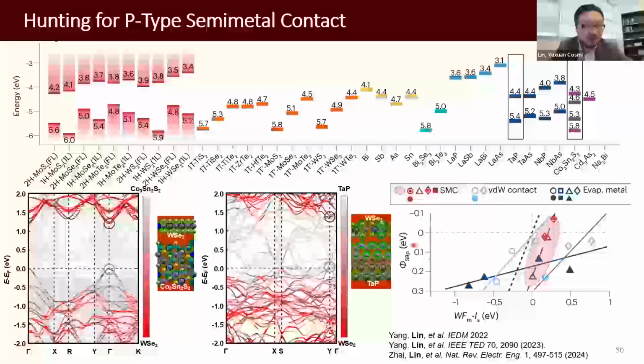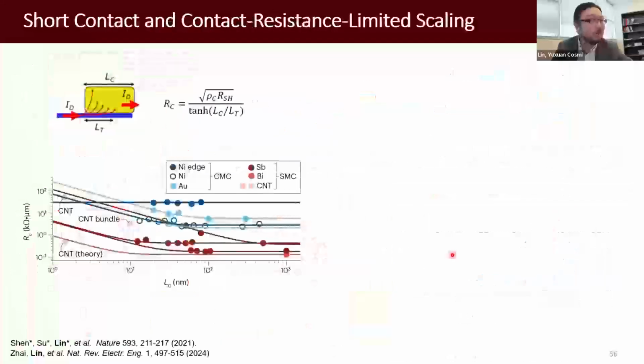And if we plot the barrier height versus the work function difference, the red ones are the simulated P-type semi-metals. So they are more or less the same slope as the ideal one, the slope of 1. So that means the Fermi level pinning is indeed suppressed.